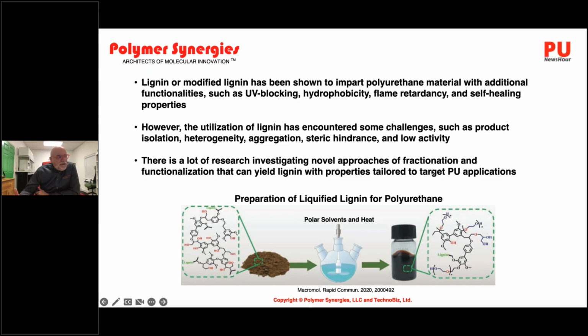Its utilization is limited because there are challenges of isolating the components of lignin, getting it to be homogeneous. It has a lot of heterogeneity, so we like materials to be homogeneous if we're going to use them in formulations. It has a tendency to aggregate because of its polyhydroxy functionality. There's a lot of steric hindrance, and it's got fairly low activity because of its network structure. But there is a lot of research going into lignin for use in polyurethanes. It can be liquefied by using polar solvents like THF and heat, and you can come out with a polyhydroxy material that's readily used in polyurethanes for elastomers, adhesives, and other applications.